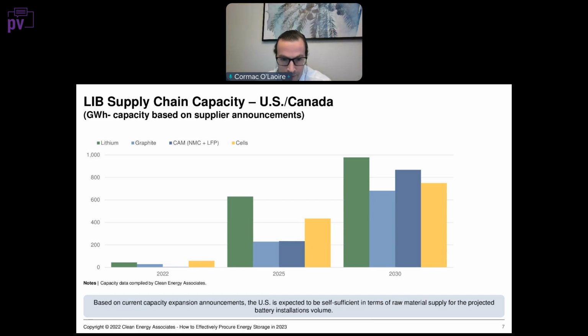As you can see, graphite in terms of projects is a little lower and not quite the amount required for the cell production if we look at 2025. But graphite production is something that scales quite quickly. So if you look out to 2030, we can see the graphite more or less mirrors the cell production. And we still see excess in terms of lithium production, but we finally see CAM production, which is going basically from zero in 2022 to perhaps, these numbers on the left-hand side are in gigawatt hours, greater than 800 gigawatt hours based on announced plans currently by credible industry players in North America.